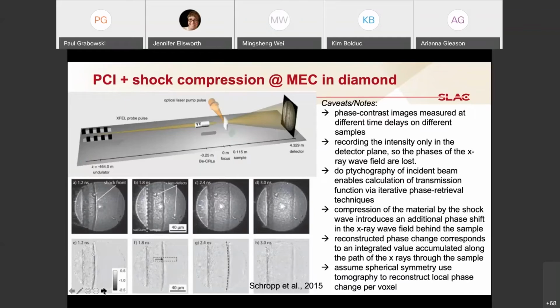Okay, so some really pioneering previous work that has deployed this setup, work by Andreas Schropp and others. They looked at diamond, a single crystal of diamond. So here are a set of phase contrast images at different time slices, and you can see in this fairly homogeneous sample of diamond, here's the initial shock front. There are some lens defects. This is effectively dust, unfortunately, on the beryllium lenses, so that's unfortunate.